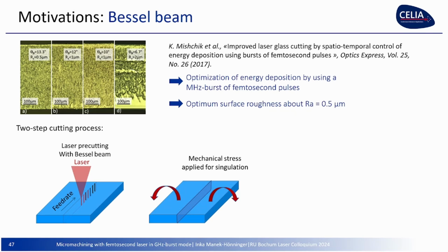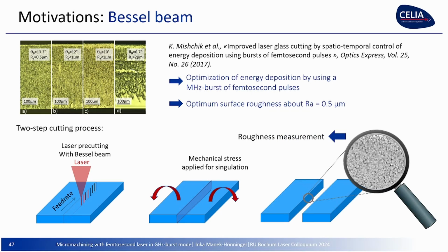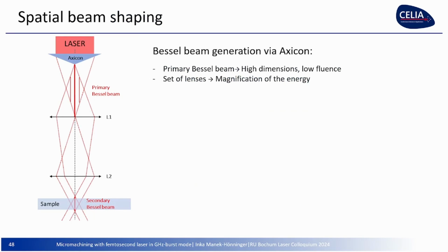the 2 pieces. And when I talk about surface roughness, surface quality, I mean we look at here, and then there was the RA. I will show you the SA result. Do averaging over a larger surface. I think it is better to give this because you can always find a line where it is very smooth, and better to take a bigger part. Okay, so Bessel beam shaping is done with a axicon. I don't know if you are familiar with that. We have a first Bessel beam, and then we have a reduction system to accumulate the energy in a small volume where we put the sample for this pre-cut.